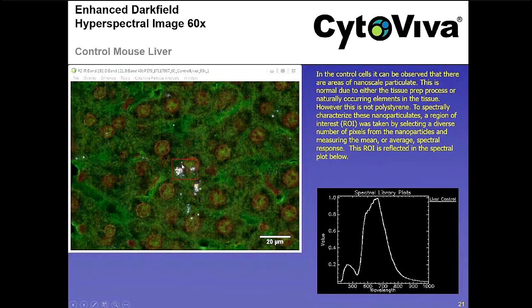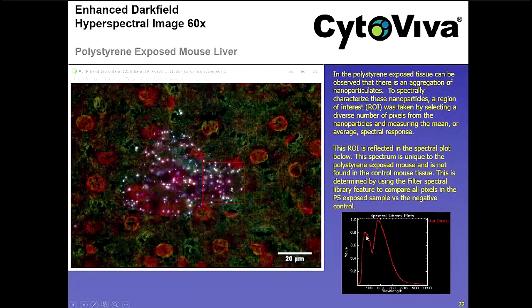Now, this mouse, of course, is going to have polystyrene particles most likely accumulating in the tissue, but it's also going to have the same material as the control mouse, right? But we see that we're collecting a different spectrum here than what we were collecting in the other. So by creating a spectral library of particulate in the exposed mouse and then filtering that against multiple negative control samples, we're able to build a positive spectral library for positive mapping of polystyrene in liver.